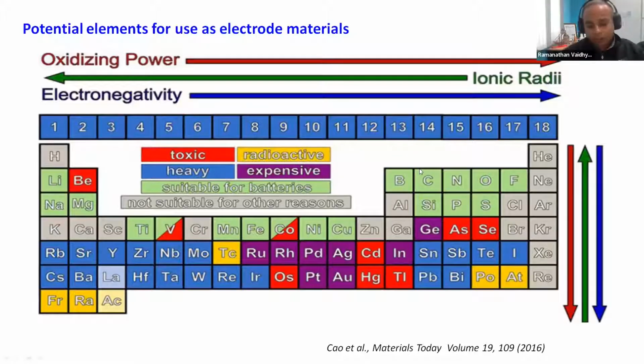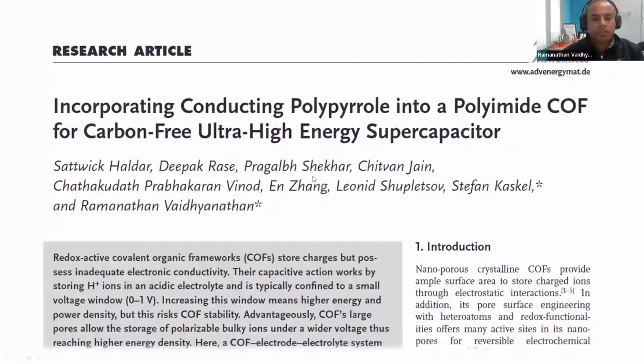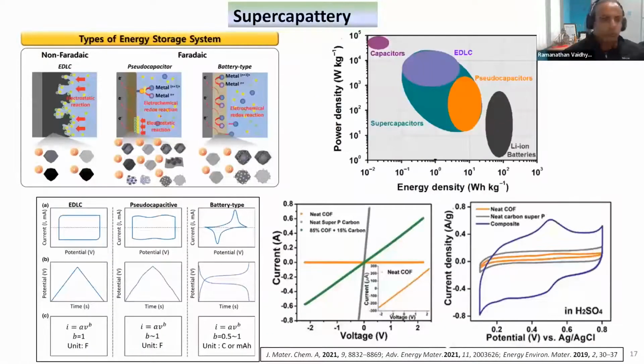So given all this knowledge that is available in the literature, we really wanted to embark on using covalent organic frameworks as charge storage devices. And so what is the idea we want? We want to make what are called supercapatteries. See here is the cyclic voltammetry representation of what a battery's CV will look like. And this is the cyclic voltammetry of what a capacitor's CV will look like. But now if you combine both of these, you can get something like this. So what is this? You do have redox active behavior. At the same time, you have a lot of surface charge storage via electrostatic interactions. And here is the charge discharge curve of a material, which will be something like this. You can see it is a combination of these two charge discharge curves, and you do have a very symmetrical curve, which is possible in potential. And why is this very good?